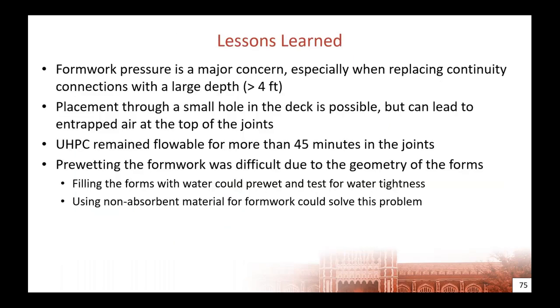So, lessons learned from this construction. As I mentioned, this was the first time the contractor had ever used UHPC, and it is a very different material. So we did have a few lessons learned. The first main one was the formwork pressure. Because of the very, very long initial set time and the fact that it maintains flowability so long, you have to be very careful about the way you design the formwork, because it won't harden up as fast as conventional concrete. So you have to have some stronger formwork.